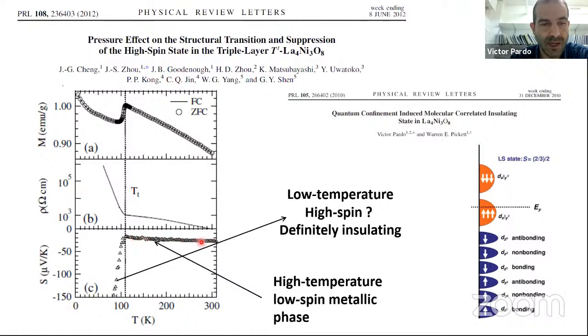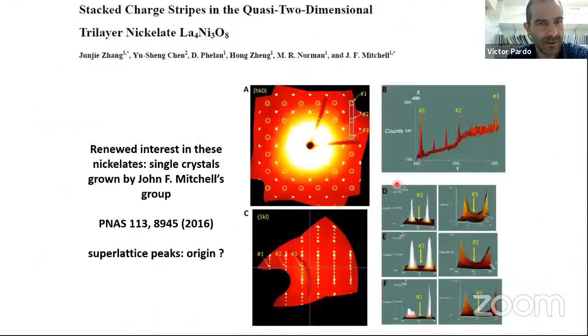The thermopower is very low at high temperatures. And even though you see the slope of the resistivity is not that of an insulator, this is because of the grain contribution. So to us it was clear that the high temperature solution is low spin, and at low temperatures you have a transition to an insulating solution. So it's definitely not low spin; it's something else. We studied this back in 2010 or so. Then in 2015, 16 or so, we came across this data from John Mitchell.